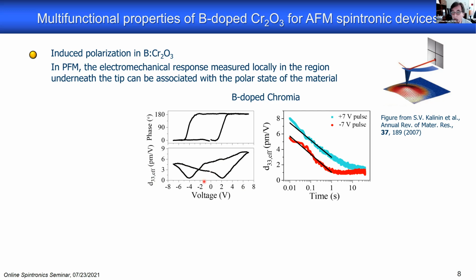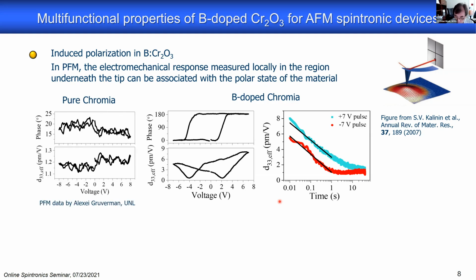However, if you have a more careful look, you see that this response is not permanent. It decays over time, slowly here on a multi-second time scale, but it will decay. So the system did not turn into a ferroelectric material. All we see here is a transient effect. It is a strong induced polarization, but quite unusual. But I stress that it's not a spontaneous polarization because the system did not turn into a multiferroic. We still have only one true order parameter here. And as a control experiment, Gruverman did the same piezo force microscopy on pure chromia films grown by the same method, and there this effect is absent.